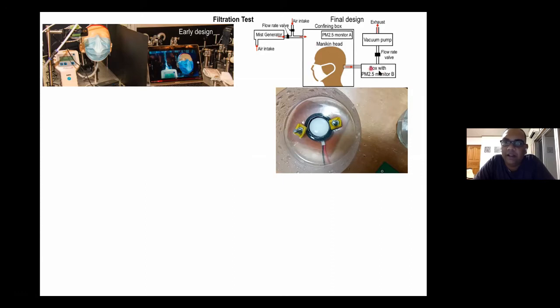So this was an idea, again, I got from Shankar Ghosh. The basic idea was, I measure the concentration of particles using monitor A before they enter the mask, and I measure the concentration of particles in monitor B after they have gone through the mask and exited through the mannequin head. Since I cannot simulate natural respiration, the inhalation and exhalation, we used a vacuum pump and sucked the air through the mask. Let me first show you the calibration tests, because this is not the industry standard testing device that is used by certification agencies, for example.